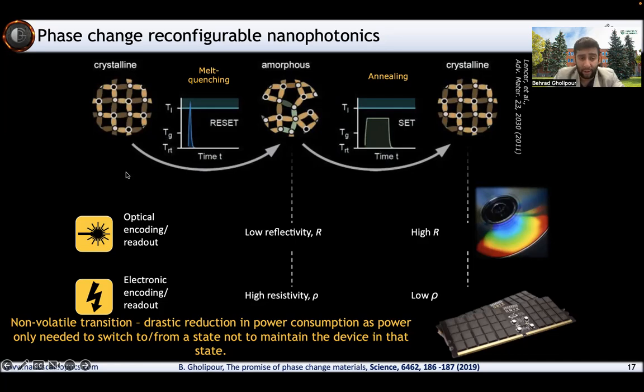In one case, from crystalline to amorphous, you melt and quench the material very rapidly, on the order of nanoseconds to picoseconds, and in some cases, people have demonstrated femtosecond melt quenching. And also, the annealing process itself is just another pulse with a slightly longer period. You don't need to make it as sharp because you're not trying to quench the material through your pulsing protocol. And just annealing the amorphous to crystalline, again, in the order of nanoseconds, you can switch the material back to its crystalline phase. And once you've switched it, you don't need any more electrical or optical supply. It stays in that state until you come back and change it. So you don't need to maintain the device in that state with energy. A major reduction in energy consumption.